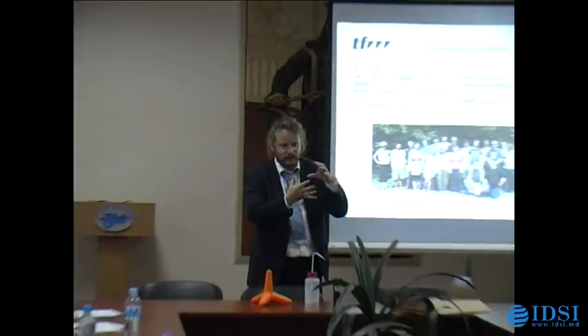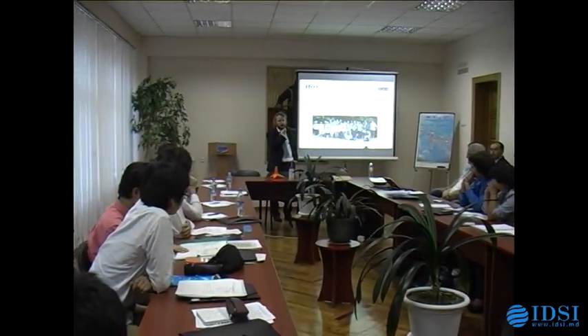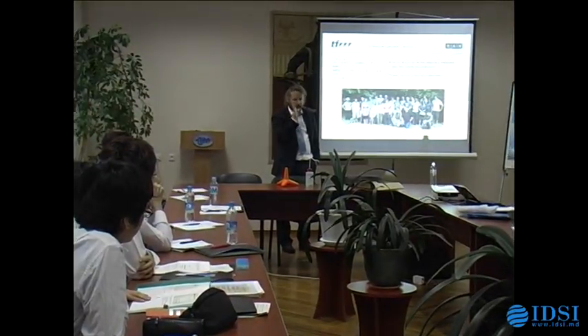Because some of these oleophobic technologies are used in mobile phones, like Sony Mobile, because their devices are now water resistant, and to wash off water or dust, they put oleophobic coating to wash all the dust or influences from the devices. So, yes, for example, for environmental protection, there are these ideas. For example, you could take this three-dimensional network like the zinc oxide, and coat it with carbon. We've done it and etched away the zinc oxide. Then you have something which is hydrophobic, but oleophilic. So this would do the trick, also soaking up oil from water surfaces. This is at the moment being discussed.